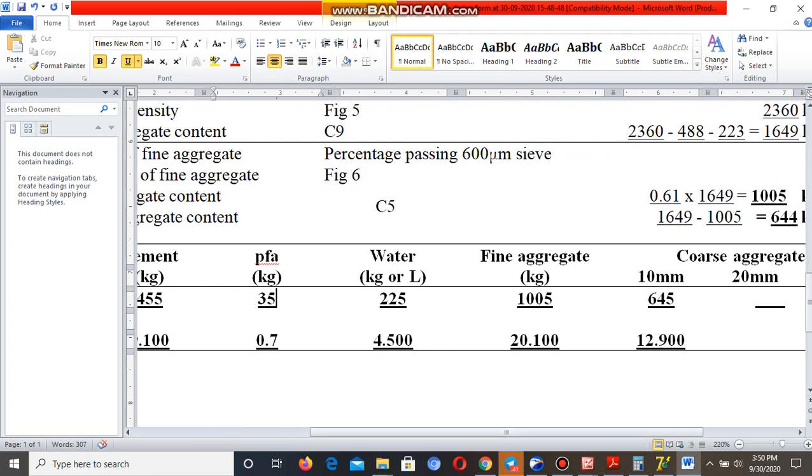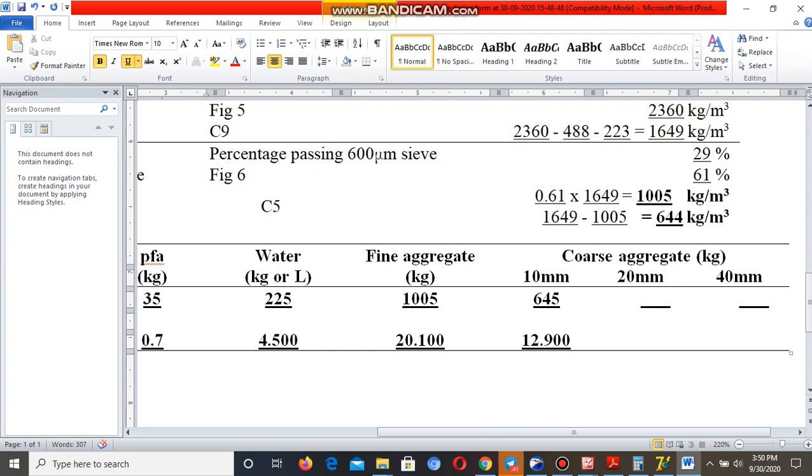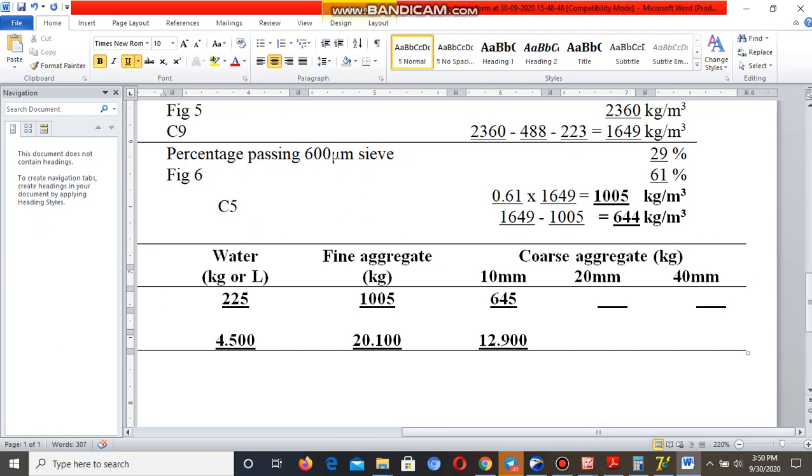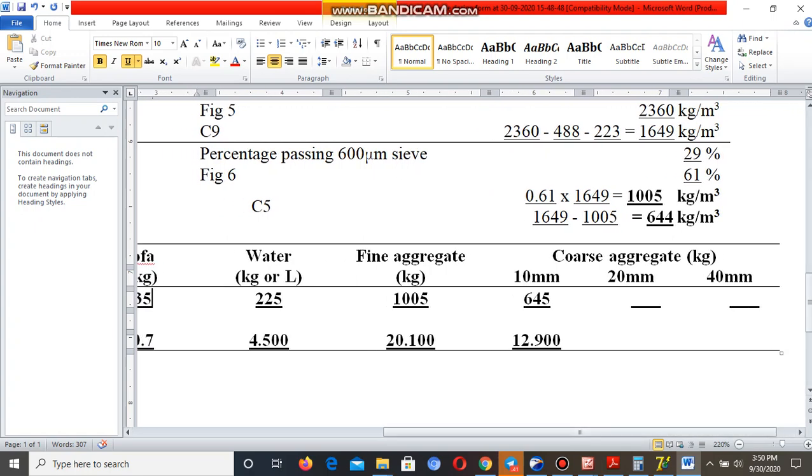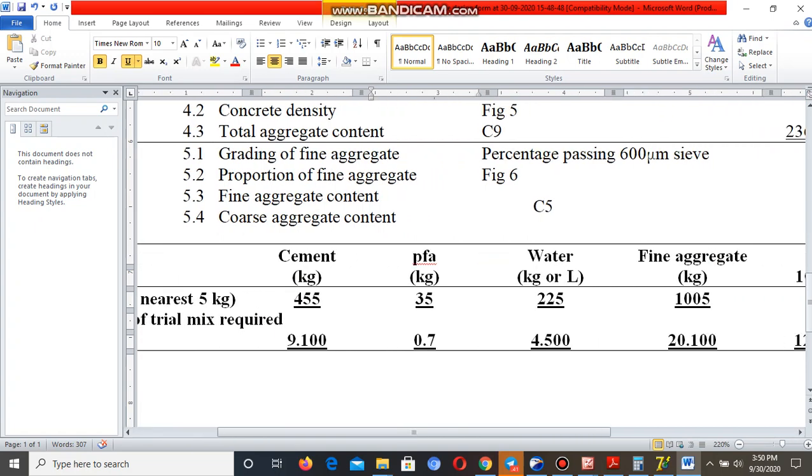We have water of 225, and we shall have fine aggregates 1005, and we shall have the 10 millimeter aggregates of 645. So these are the fine aggregates, and these the coarse aggregates. For coarse aggregates, we don't have 20 millimeters, only 10 millimeters. So that's our mixed design.